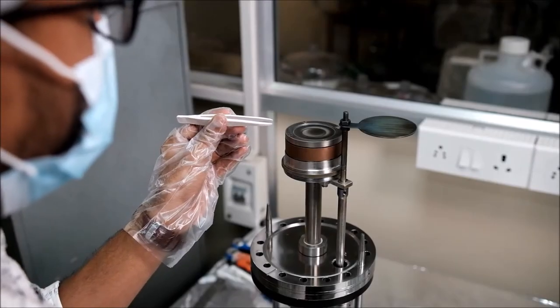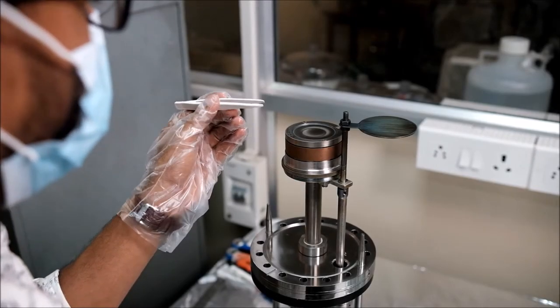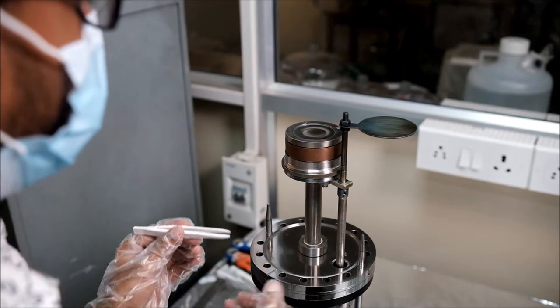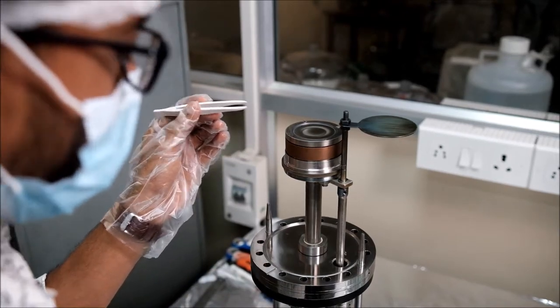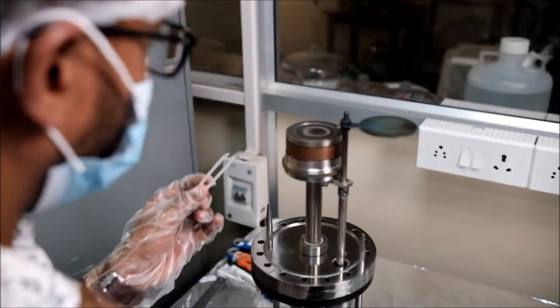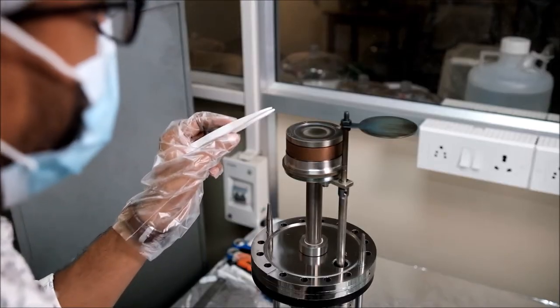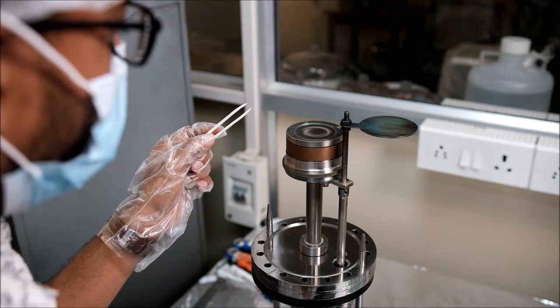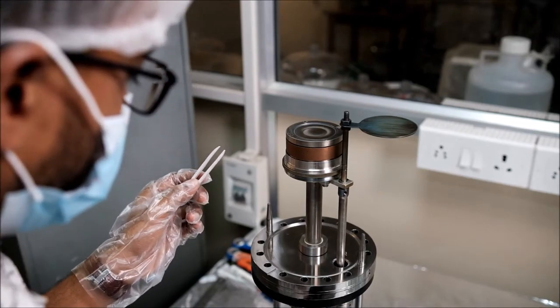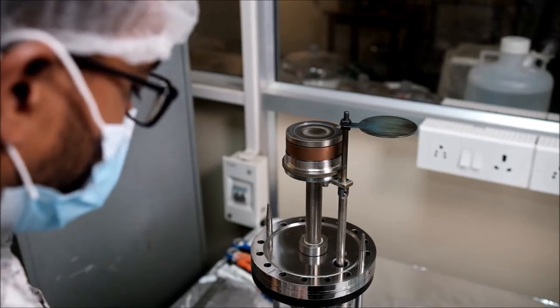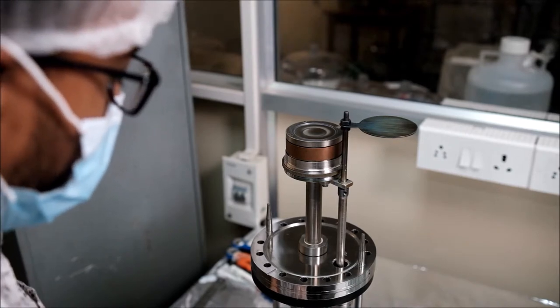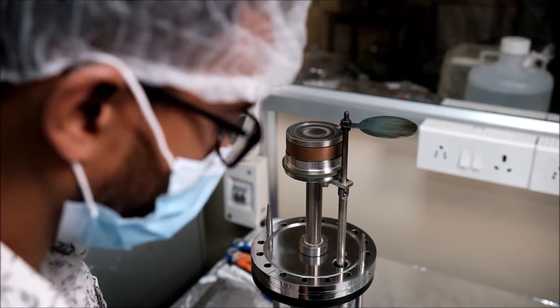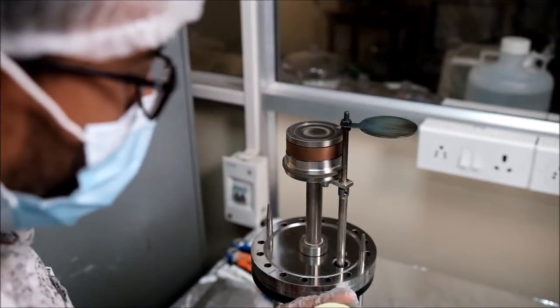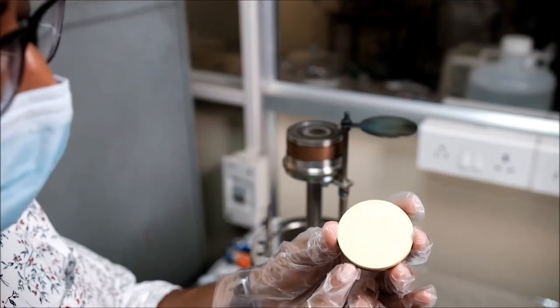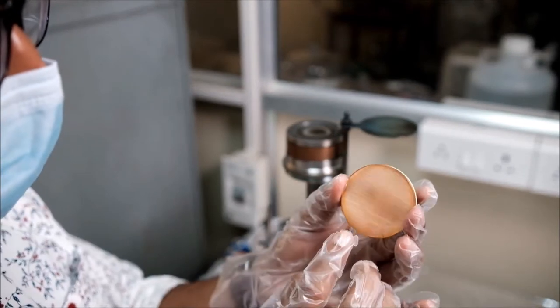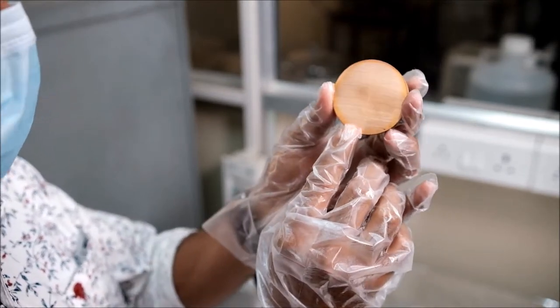The heat dissipation issue mainly arises when we use an oxide target, because oxide targets are not good heat conductors. So to mitigate this heat dissipation issue for the oxide target, we take a number of steps. The first step is we always pass chilled water through the target to dissipate the heat. And the next part is, when we use the oxide target, this is a tungsten oxide target, at the back of it we use a copper backplate.